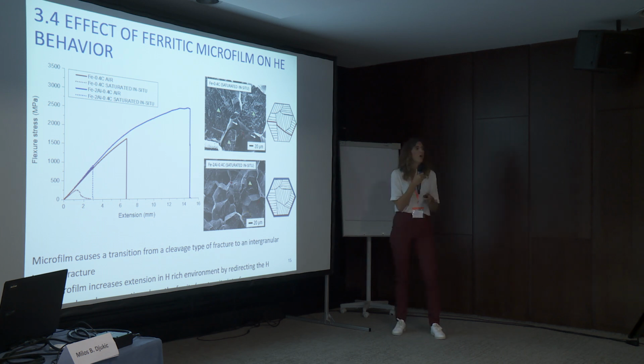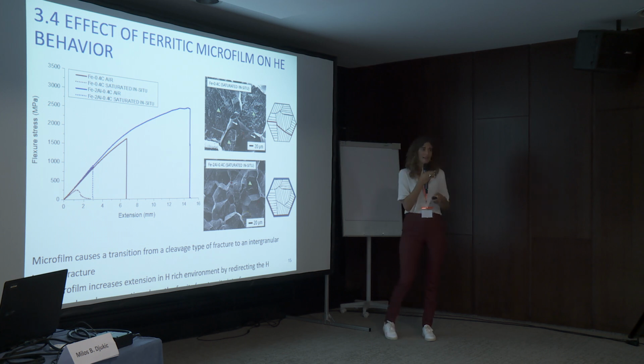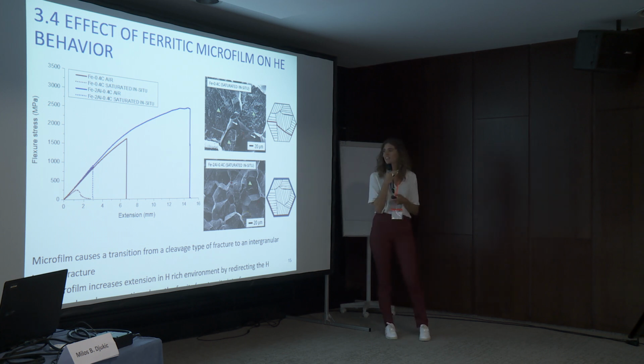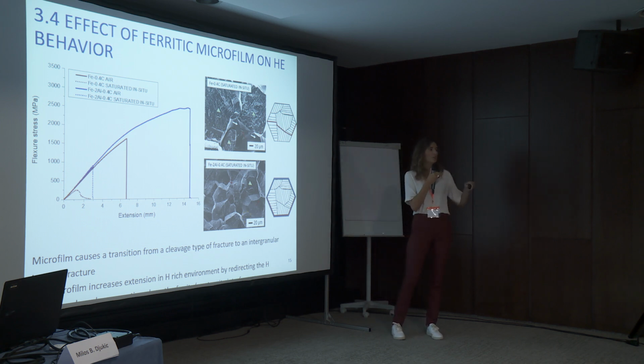How does this come? Well, this in fact comes from an interplay of the HEDE and the HELP mechanism, where we really have decohesion of the martensite-ferrite interface. So the microfilm can extend the elongation in mechanical loading in a hydrogen-rich environment just by redirecting our crack propagation path along this interface and away from the weakest link, which are the packet and block boundaries.